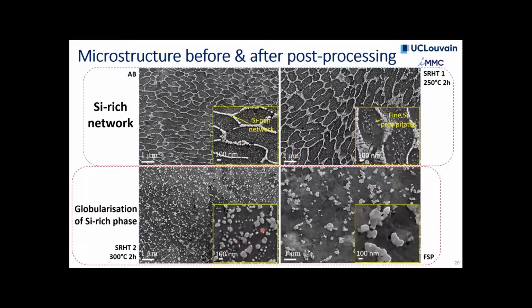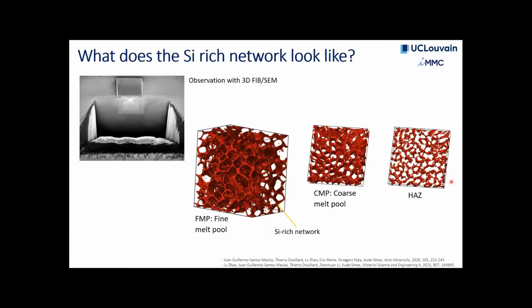In terms of damage mechanism, here are the microstructures of the different treatments that we considered: as built, stress relieved at 250, and stress relieved at 300 degrees, and then after friction stir processing. And so you can see that these two conditions lead to very highly connected microstructures, while here you have a much more globularized microstructure. And this will lead to very different damage mechanisms that explain the mechanical properties.